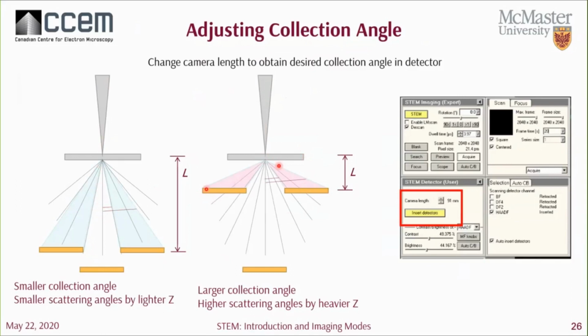There are references out there that have simulated the scattering cross-section, which you can use to determine the collection angle for your detector, and what kind of collection angle you need for your particular sample. But it's a general rule of thumb that you probably just adjust your camera length to have an inner collection angle of at least 50 milliradians, if not greater.